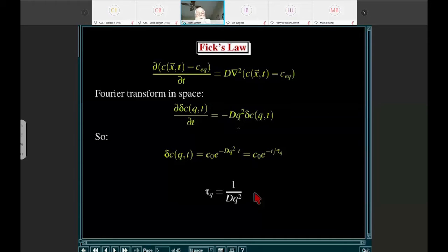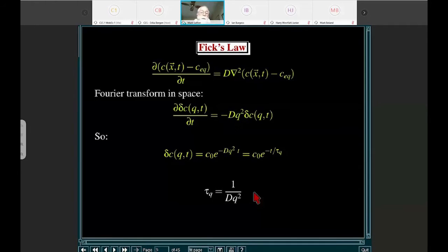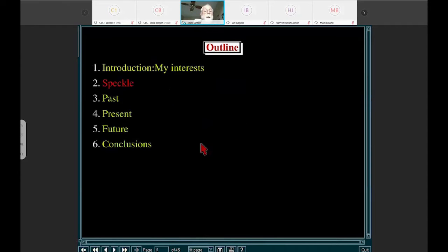And the time constant is simply the coefficient of the diffusion equation, which is 1 over D Q squared. So the first point I'd like to make, emphasizing XPCS, is that by measuring the time constant as a function of reciprocal space value Q, what you get is a Fourier transform of the equation of motion of the system. And if you want to explain behavior of materials, you'd like to do that. The other point I'd like to mention at this point is that we'd like to directly probe the fluctuations and not so much the average structure.